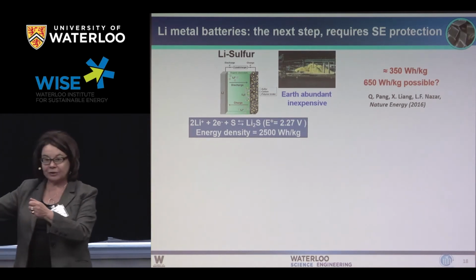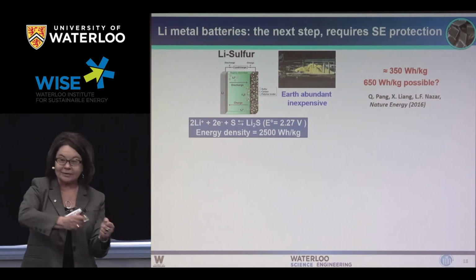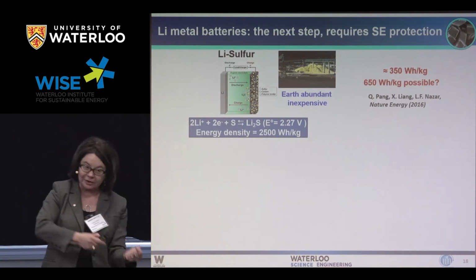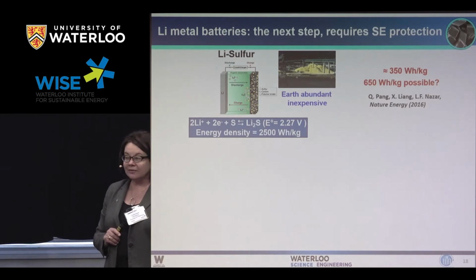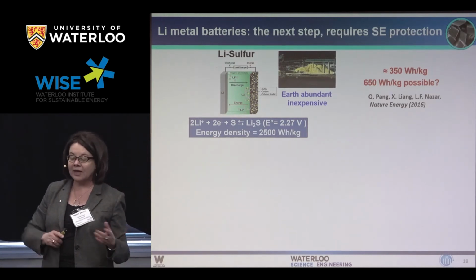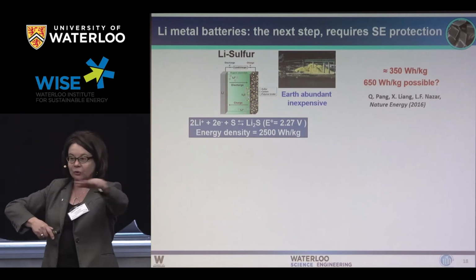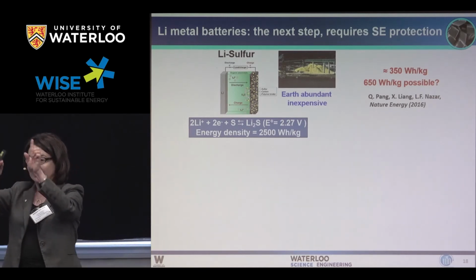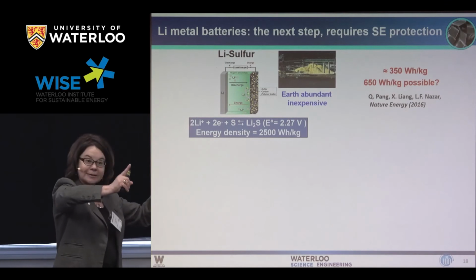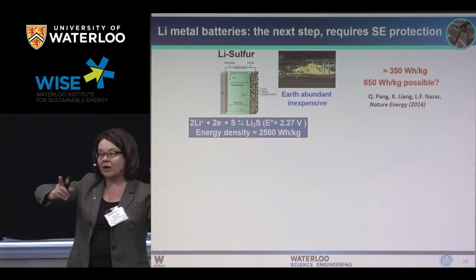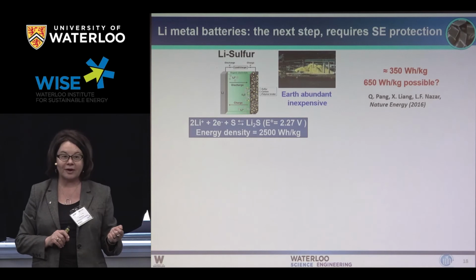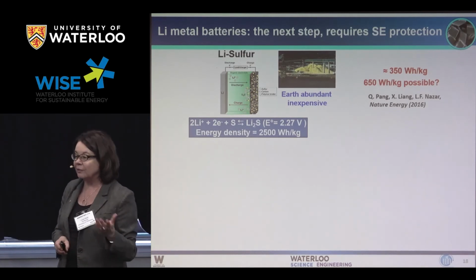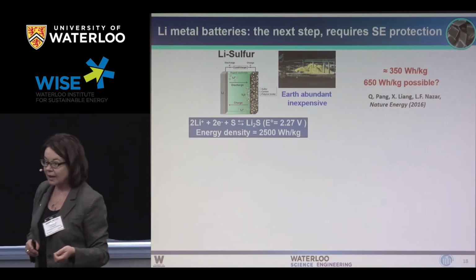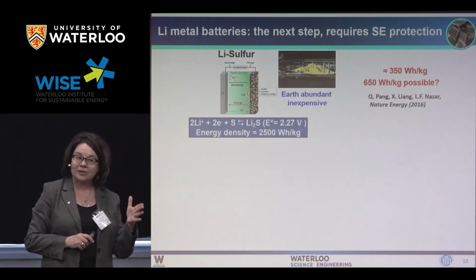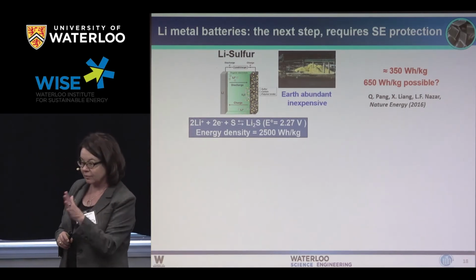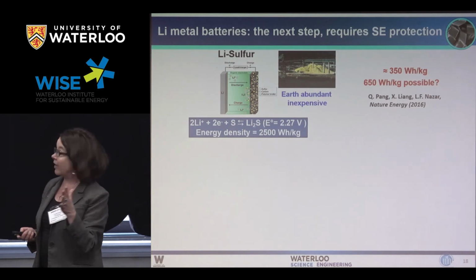So in the battery, as I mentioned, the lithium ions and electrons have to plate and go back and forth. They have to deposit and redeposit. And in the case of lithium metal, for reasons we still don't understand, they don't do that homogeneously. So they don't do it as a flat surface. And you end up with these little spiky growths, which is what we call dendrites. And they pierce the separator in the cell, and they cause a short circuit. And that's what causes the fire. So since then, we've been struggling with trying to understand how to control this. And I would say that we're on the cusp of understanding. The world, my community, is literally the last few years really advancing this.